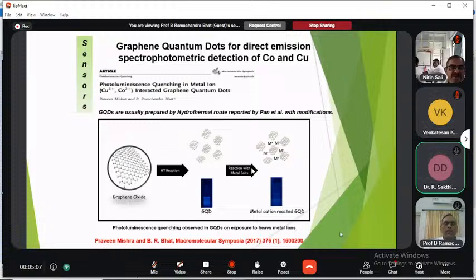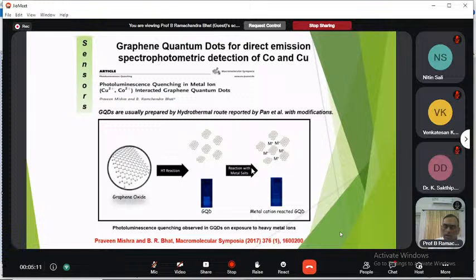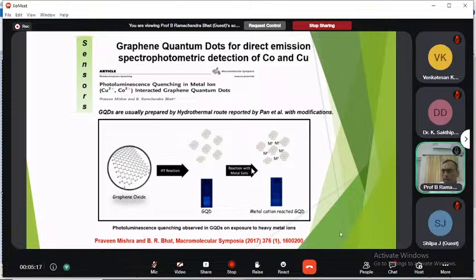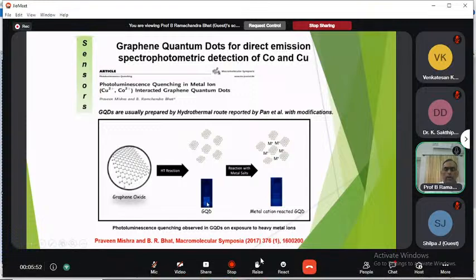We'll continue with this. The graphene quantum dots, we have used this graphene quantum dots as a sensor for the cobalt and copper metal. As you know, the copper and the cobalt metal is also required for our body to function. But at the same time, if the concentration is high, then you will have side effects. So what happens here is the graphene quantum dots: graphene oxide is taken at a high temperature, it is broken into small pieces and the quantum dots are obtained. You can see the PL here and glow.